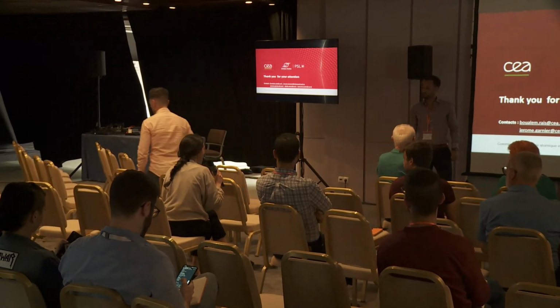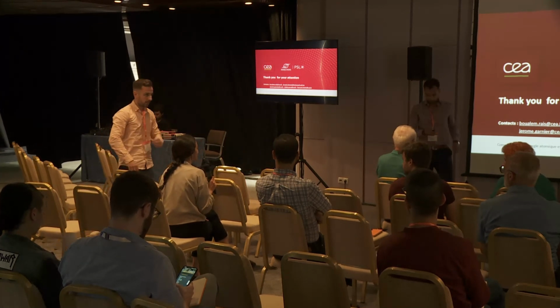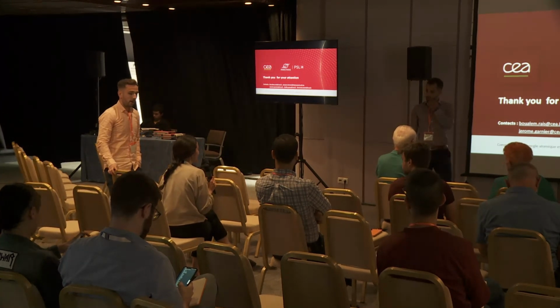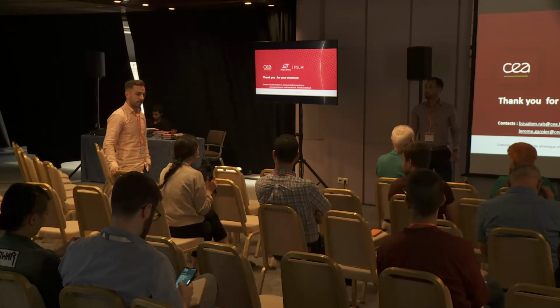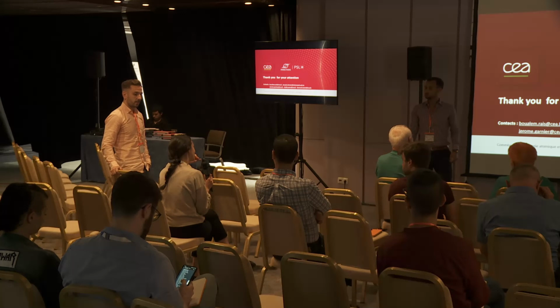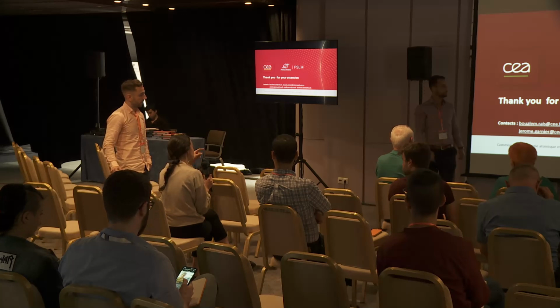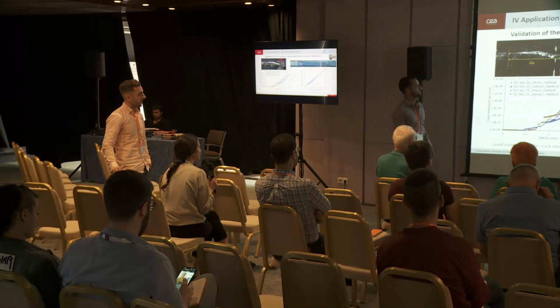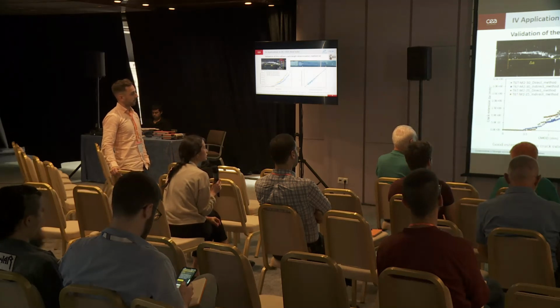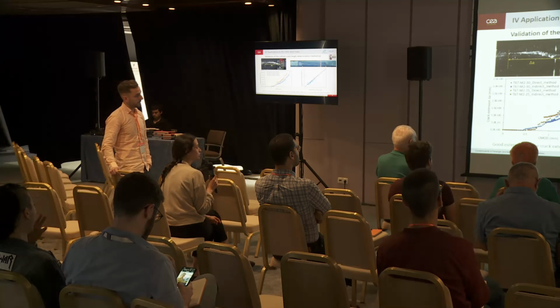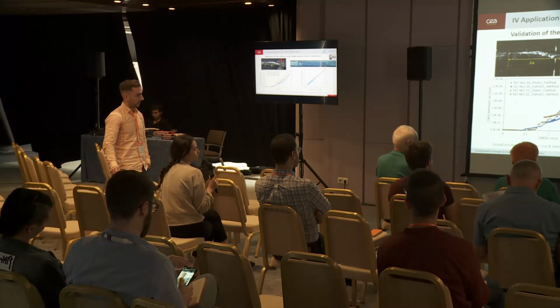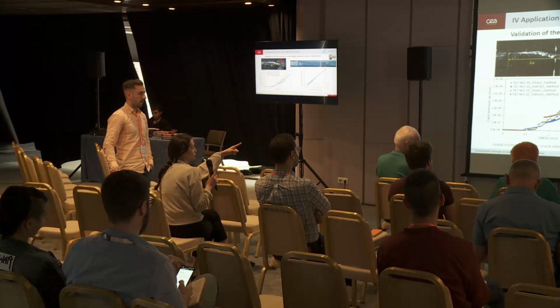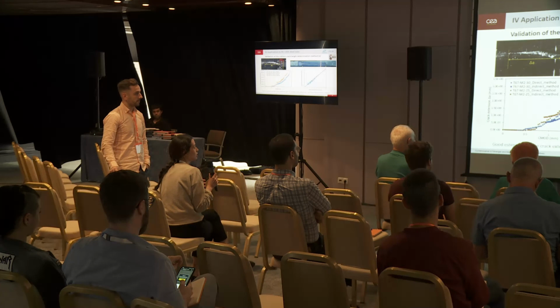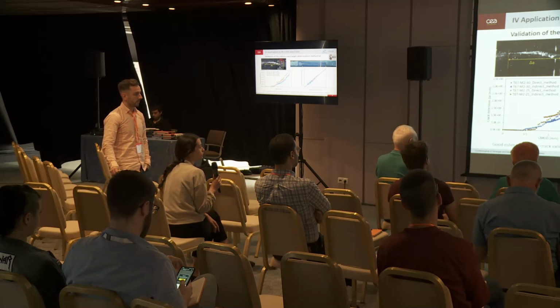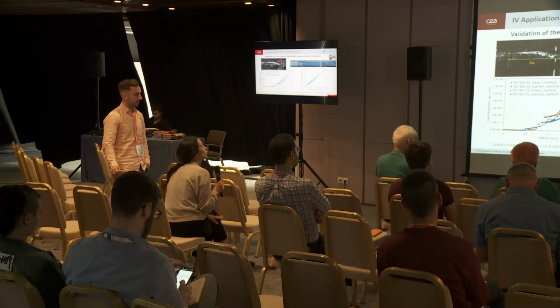Hi, thank you for your talk. When you compare the crack length in your indirect method with the direct method, in the direct method what you are measuring is on the external surface, right? And the crack front is not completely flat, right? Yes, but there is not a big difference. Okay. And you assume that there is no difference during the whole propagation, right? Because maybe in the beginning you have a bit more difference. Here, yes, there is a little difference, but I don't consider it, and that's why I have this scatter. Okay. Good. Thank you.